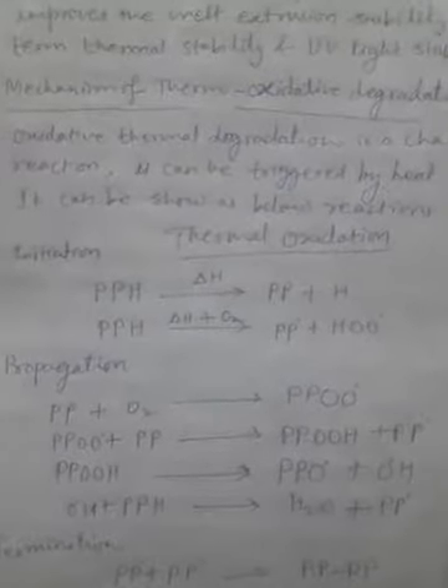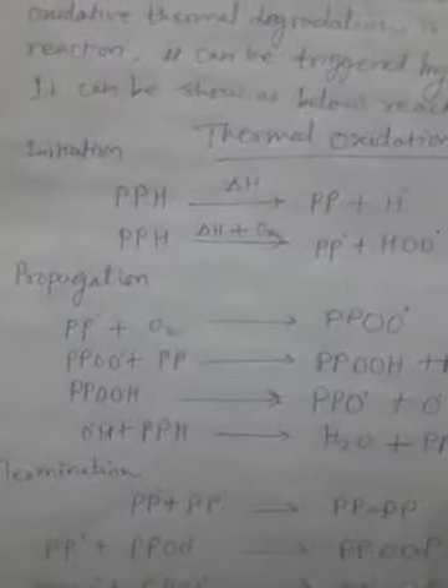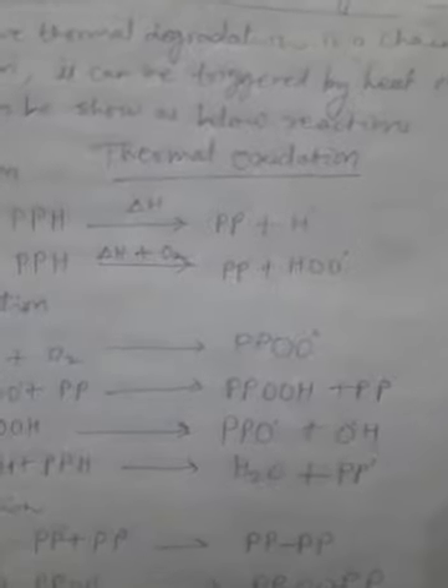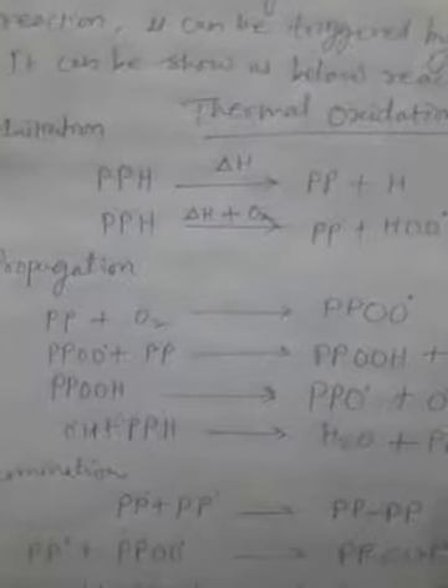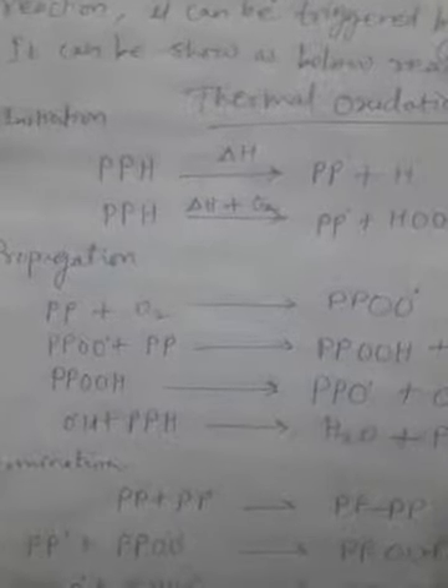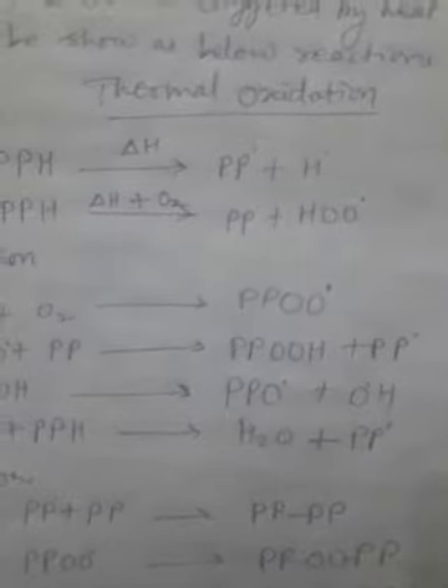You can see here that the oxidative thermal degradation is a chain reaction. It starts somewhere in the middle or at the end, at any place where, by the application of heat, it is triggered and converted into free radicals. In the reaction initiation, the polypropylene molecule is heated and split, one hydrogen atom gets separated, and PP dot plus H dot, both are free radicals and highly reactive in nature. This is just the thermal degradation reaction, and here another, PPH, in the presence of oxygen, may convert into PP dot plus HOO dot.